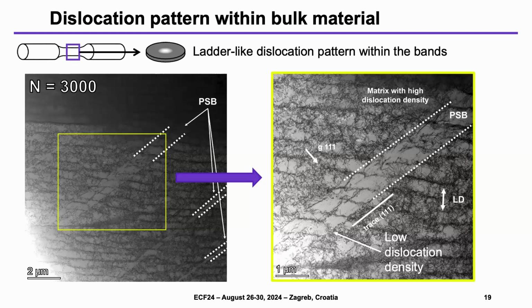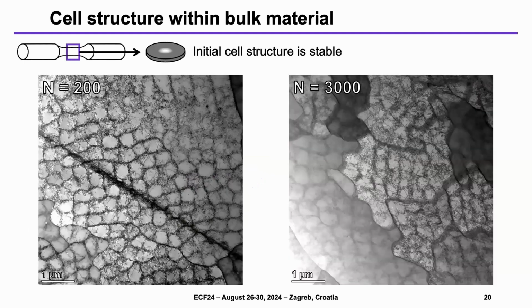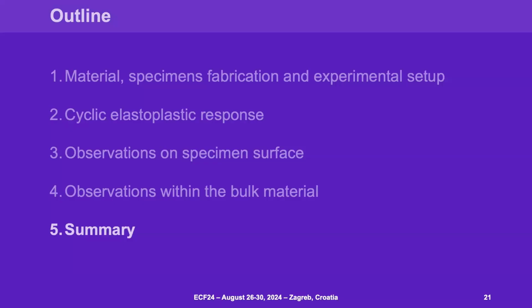The initial cell structure, on the opposite, compared to the bands, remains almost stable during cyclic loading. And this was confirmed also by other TEM images, which were acquired on different, let's say, crystallographic planes. So as you can see, after 200 and 3000 cycles, the cell structure remains almost stable. Okay, so with that, I conclude my presentation with just a summary.